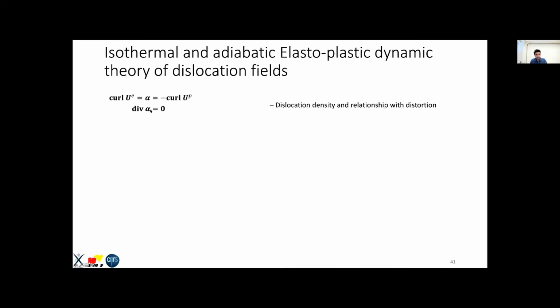What this says is that dislocations cannot end inside the material. They can be present either as loops, or end at boundaries of the domain, or end at each other. This equation essentially tells you that it's a solenoidal field, so it is divergence free because the divergence of curl is equal to 0.